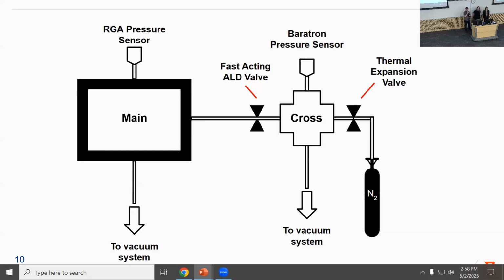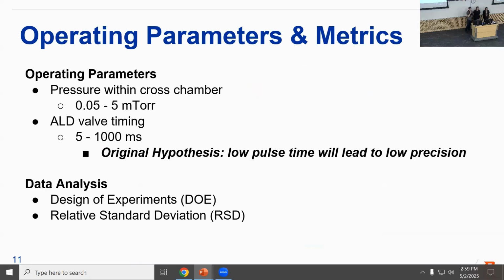But in the main chamber, this is ultra-high vacuum, so we use an RGA pressure sensor. This is a residual gas analyzer, and it's basically just a small mass spectrometer. It ionizes the gas, and then it counts the number of nitrogen molecules based on their mass. So a small amount of that nitrogen will flow through that fast-acting ALD valve into the main system, and then we'll analyze the pressure difference.